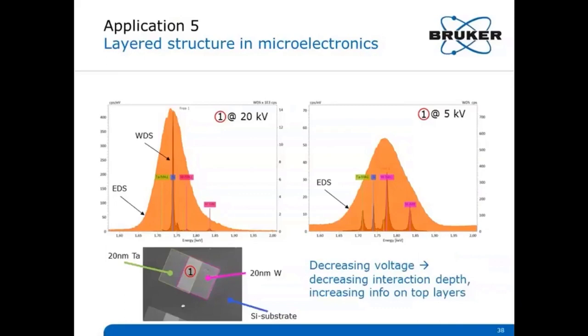At first, we see results of point analysis. We made an analysis here right in the center where the two layers are overlapping. The slide shows two WDS energy range scans, one here, one there, along with the EDS spectrum section acquired at different acceleration voltages. To the left, acquired at 20 kV, and to the right, acquired at 5 kV. The spectra indicate the electron interaction depth in the layered sample.